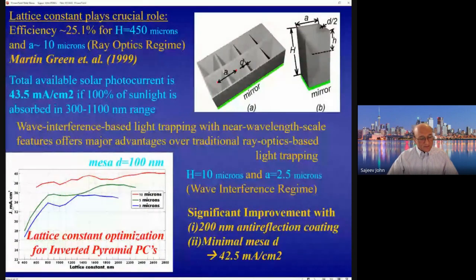And here you see some calculations using finite difference time domain of the photocurrent density that can be obtained as a function of the lattice constant A of these structures, for different structures of height ranging from 3 up to 10 microns. So at 3 microns, the optimum lattice constant is about 1.3 microns. As you make it thicker, at 5 microns, it's about 1.9. And then finally at 10 microns, the optimum is 2.5 micron lattice constant. And here we see a photocurrent density of about 40 milliamps per square centimeter.